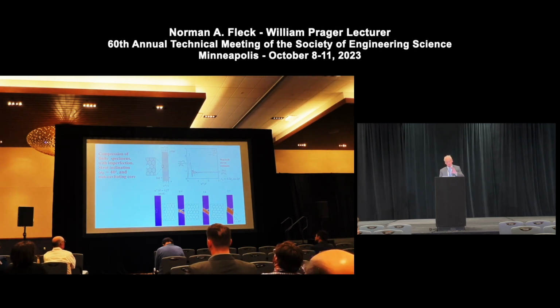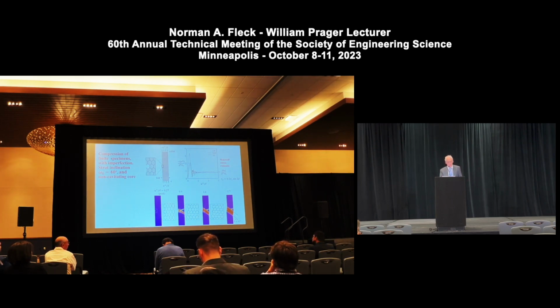So the simulation I'm now talking about is the compressive loading of a specimen, say with an edge imperfection, and you see that the shear band propagates across and then band broadening occurs. Here's the simulation, which I think I showed before, of the axial response. The plateau value of that stress can be directly related to that shear stress, the Maxwell stress in shear. And when you compare the two calculations, one of the structural response and one of that separate Maxwell stress evaluation, there's good agreement between the two. So there's a very close analogy between this instability propagation of a shear band in the non-cavitating honeycomb with its strongly softening behavior, followed by an instability which can be well modeled by the Maxwell stress.